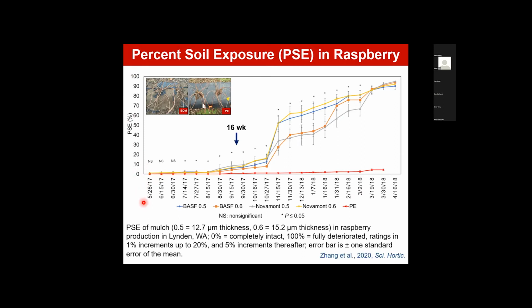And so you can see from this particular period from May 2017 to April 2018, we have changes in percent soil exposure based on these different materials that we're testing. And in this experiment, we tested 2 ecovio or BASF biodegradable plastic mulches at 0.5 and 0.6 mil, and 2 Novamont or Mater-Bi feedstock materials that are biodegradable plastic mulches at 0.5 and 0.6 mil as well, and contrasted that to polyethylene mulch.